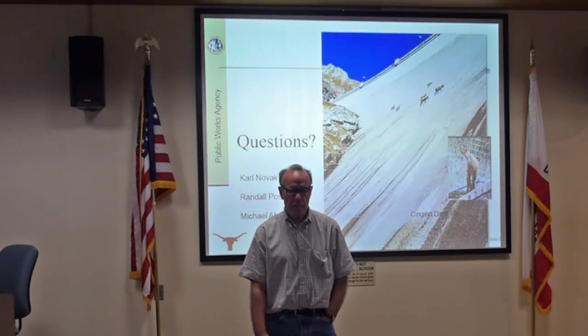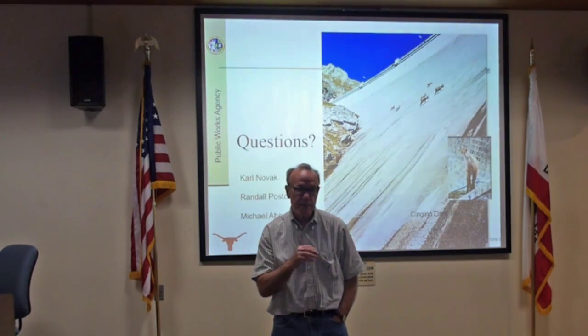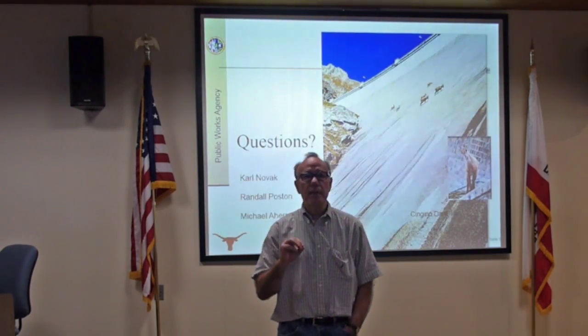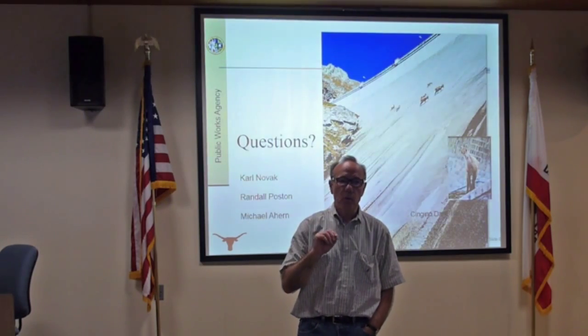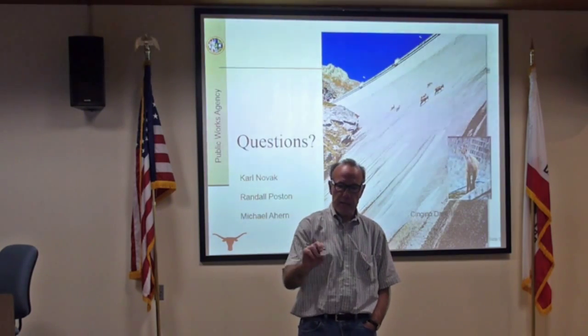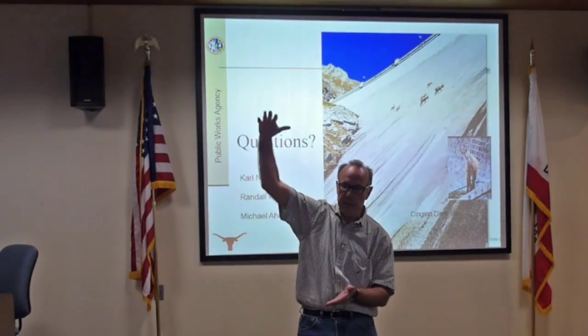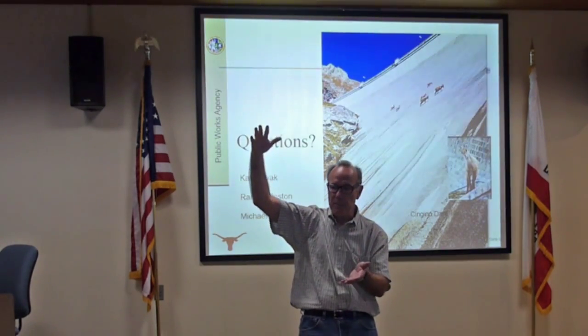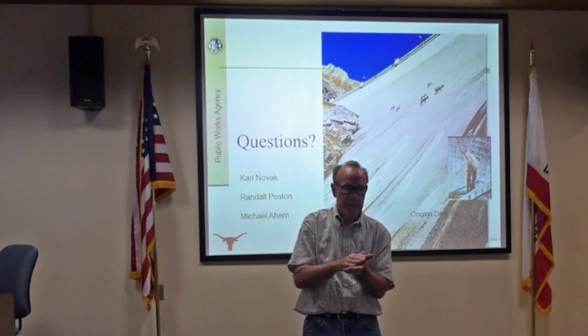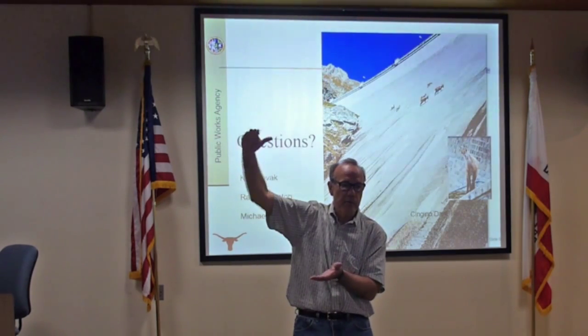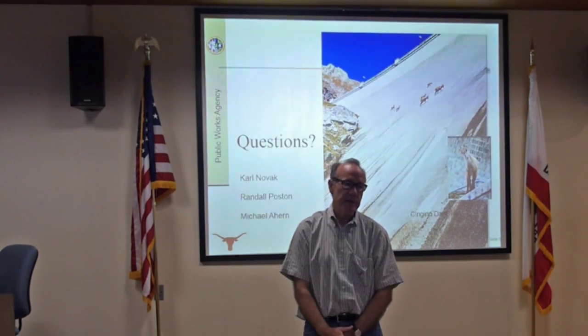Calcium nitrite is the most popular one, and you can think of it as kind of raising that chloride corrosion threshold. Instead of it being like 300 parts per million, it's increased to a couple thousand parts per million. So effectively, that makes it a much higher threshold before corrosion can actually occur.